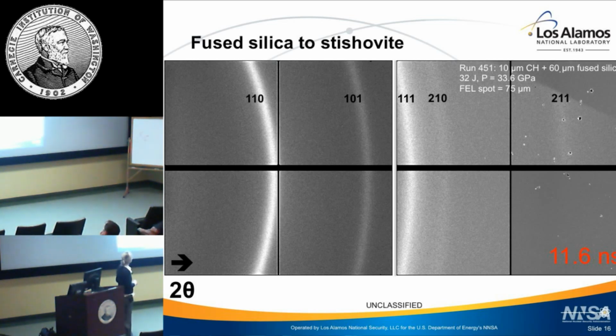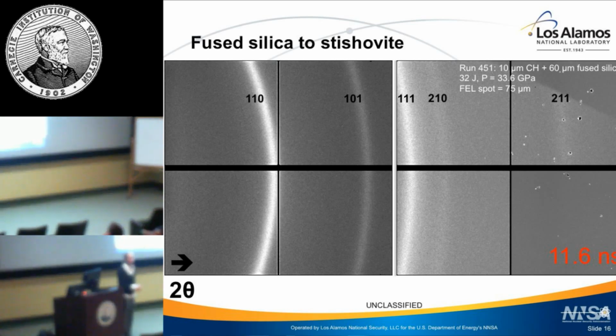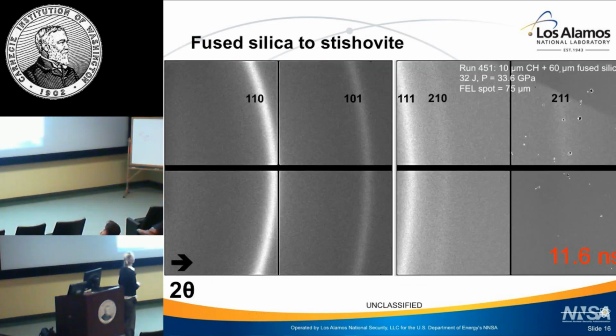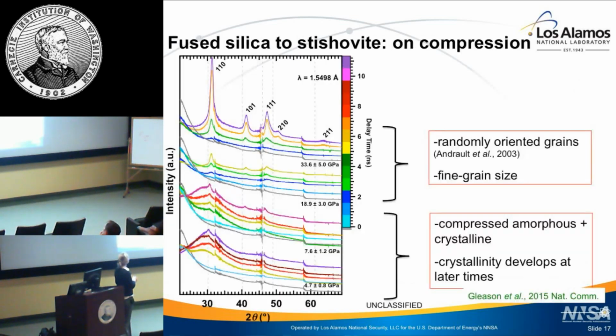If we now integrate this pattern and look at a set of different pressures, so here, let me orient you. This is intensity as a function of 2 theta. I've clustered my pressures, so here's about 5 GPa, 7.5, 19, and 33, okay? And I've color-coded the different time delays. So traversing the entire sample is about purple, or 11.5 or so nanoseconds, and then earlier time delays are different rainbow colors. So let's pull this apart a little bit.